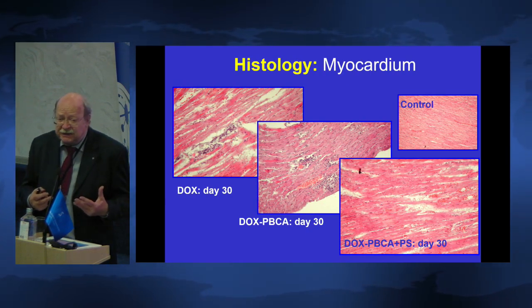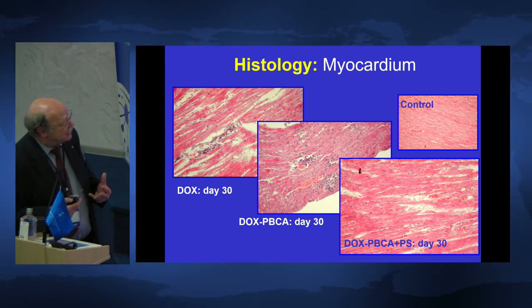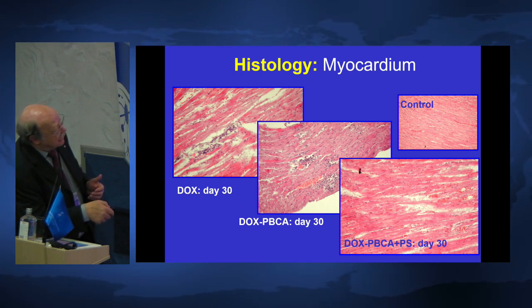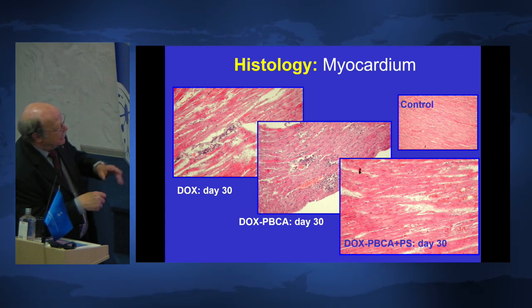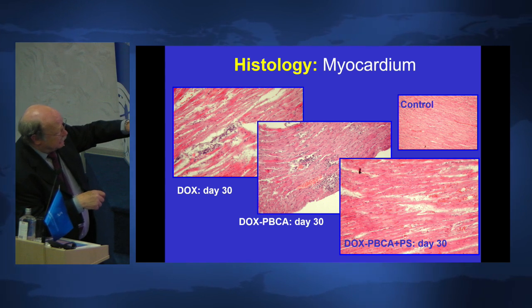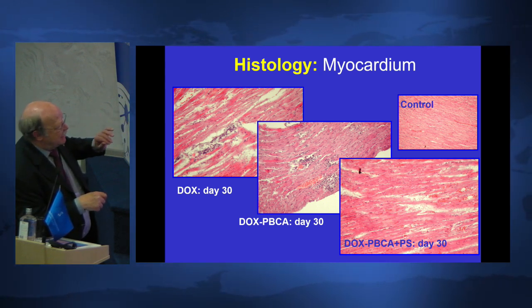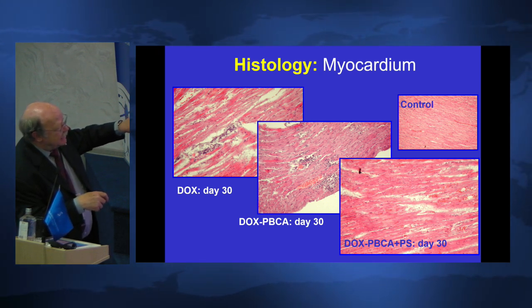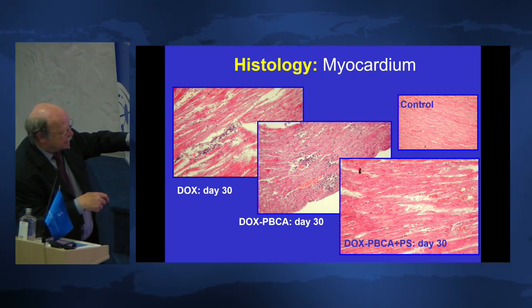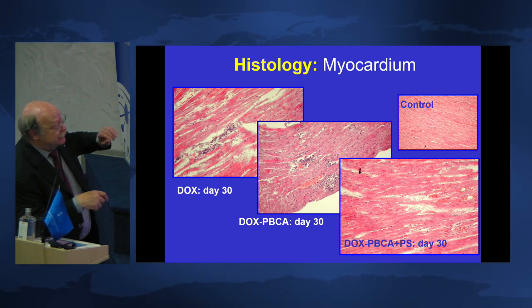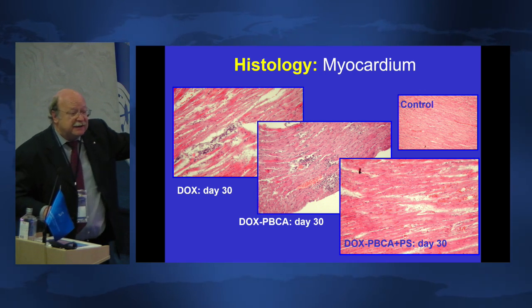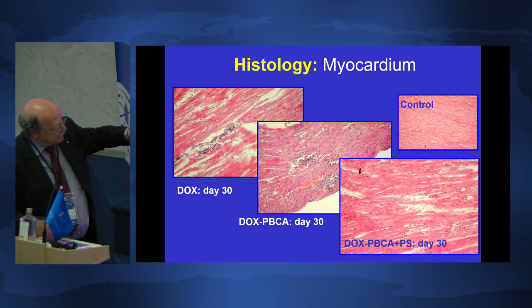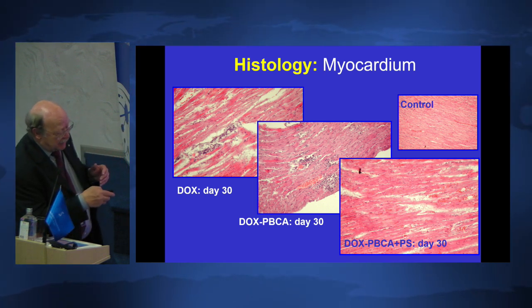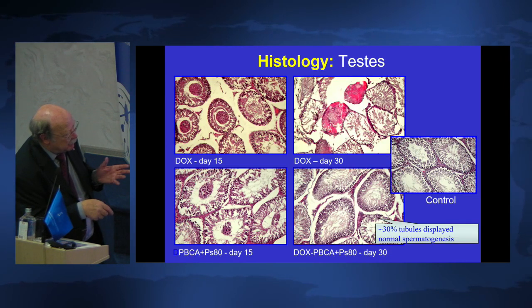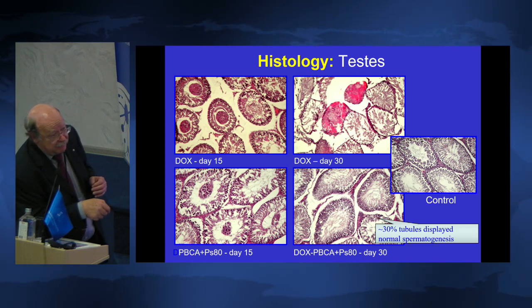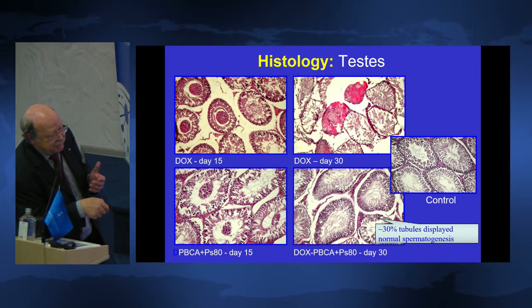You see, with doxorubicin, the main toxicity is heart toxicity, myocardial toxicity. And you can see here that the control is a healthy myocard. And then you see doxorubicin solution, after day 30, it has some severe detrimental influence. And as you can see with doxorubicin polybutyl cyanoacrylate nanoparticles, it's getting much better. Already Couvreur knew this. But when you overcoat them with polysorbate 80, it's getting even better. So the damage done by the doxorubicin is decreased by the treatment with the nanoparticles.